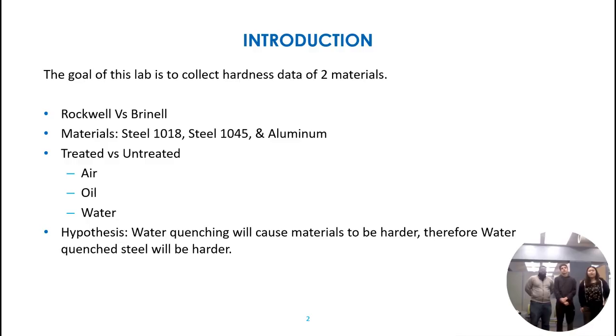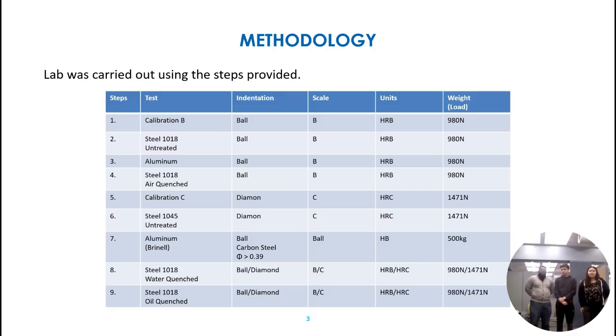Our hypothesis is that water quenching will cause the materials to be harder, and therefore the water quenched steel will be harder. The experiment was done according to the steps provided in the table. Calibration B was done with a ball tip. Calibration C used a diamond tip, and step 7 used a Brinell tester with a 500 kilogram load.